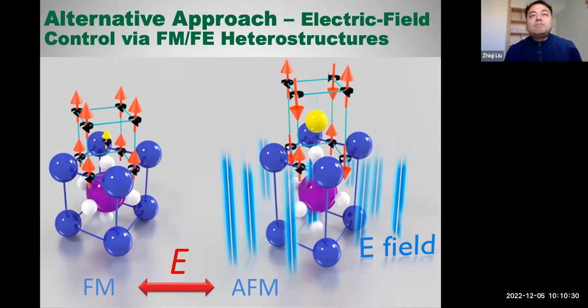So there's no difference then. But if we apply an electric voltage to an insulator, for example, a piezoelectric material or a ferroelectric oxide, the electric voltage could only generate the piezoelectric strain rather than an electrical current. So we want to utilize a functional oxide, insulator oxide, so that the electric current is suppressed and then the Joule heating is suppressed.